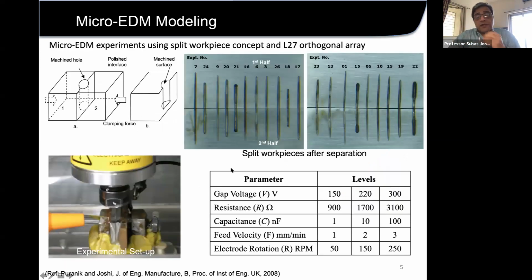Similarly, at that time there was no understanding of how deep a hole can be made in an EDM process, and what is the shape of the hole which is made. So we devised a method. I don't say it is a great method, but what we did is we had two very polished surfaces, and then we joined those surfaces together firmly, and then we actually made these EDM micro holes in between the two surfaces, which are held by some kind of vise.